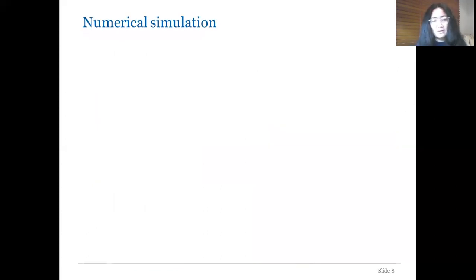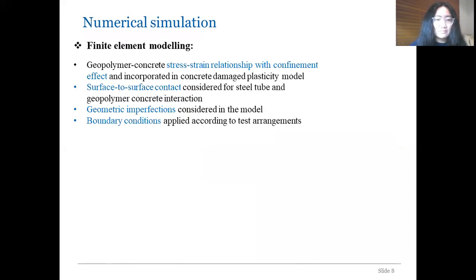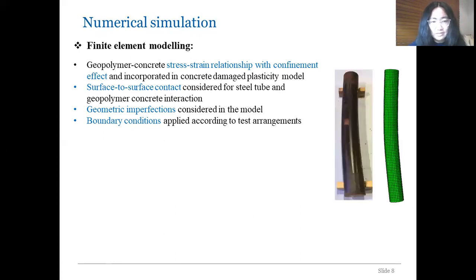Apart from the experimental investigation, I also performed a numerical simulation because it is more cost efficient to investigate a large number of geopolymer concrete structures in numerical simulation. So I firstly developed the FE model in ABAQUS by incorporating the material properties of the steel tube and the geopolymer concrete infill. For the geopolymer concrete in particular, I developed the stress-strain relationship with the confinement effect incorporated. Surface-to-surface contact was considered for the interaction between the steel tube and the geopolymer concrete infill. Geometric imperfections were considered in the model, and boundary conditions were also applied according to the test arrangements.